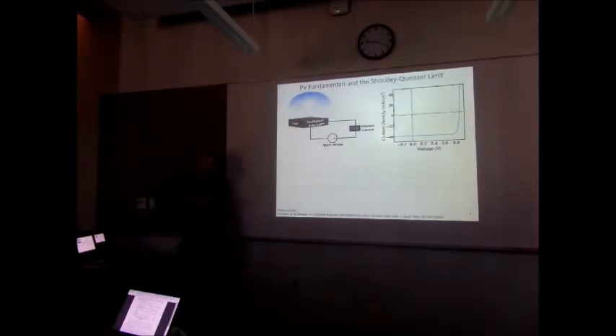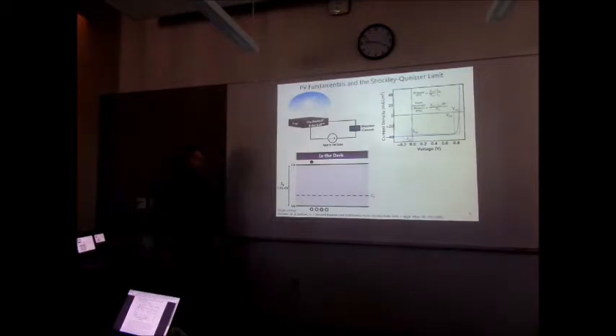So how we measure the efficiency of these solar cells typically is we apply a voltage when it's under light and we measure the current. This is called a JV curve. You can define what's called the short circuit current and the open circuit voltage here. We can also define an operating point, and you want to maximize the current voltage product because power is equal to voltage times current. And we can also define the fill factor, which is just the ratio of these two products, and then multiply them all together and divide by the power in to get the efficiency. So this is what I want people really to key in on here, is that there are three parameters that we're trying to maximize when improving the efficiency: the open circuit voltage, the short circuit current, and the fill factor.